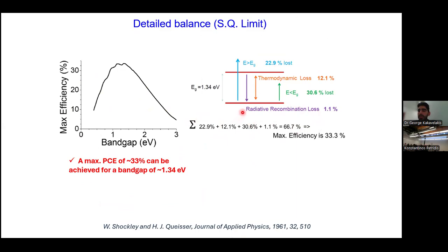Okay, if we consider the photons that cannot excite electrons, so energy lower than the energy band gap, they are around 30.6%, so one third is already lost. Around 20 to 25% approximately are these thermalization processes that occur because of the high energy photons. And we mentioned the electrons then need to relax to the minimum of the conduction band for the current to start to flow. Okay, so already more than 50%, and the rest is thermodynamic losses because of the material and also the position between the solar cell and the sun, as well as the material impurities.